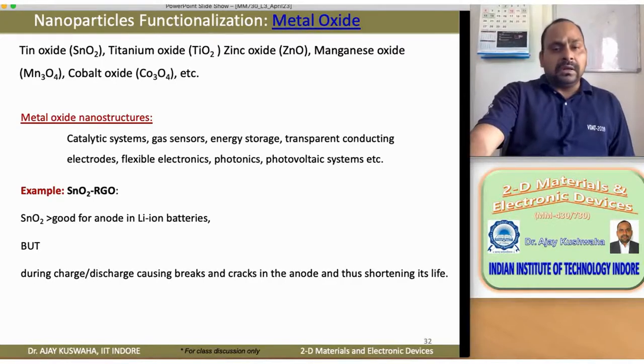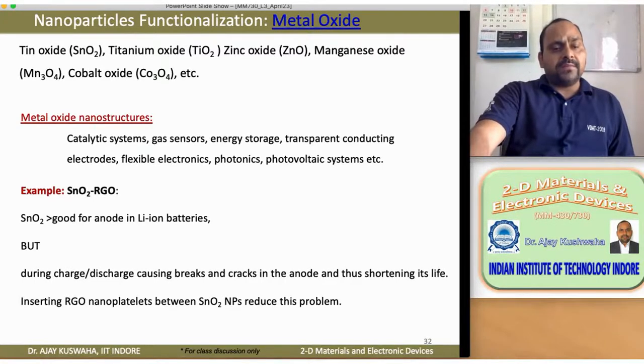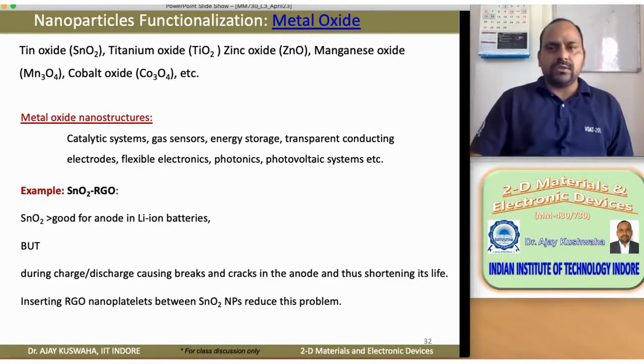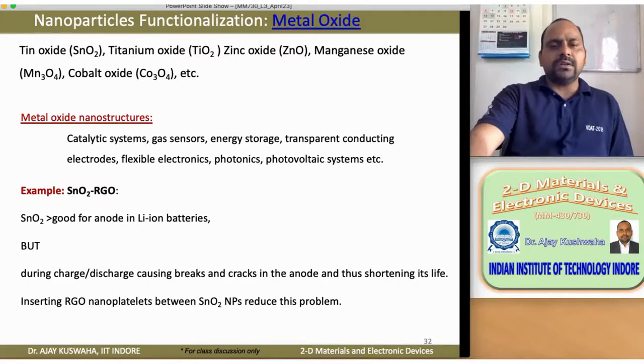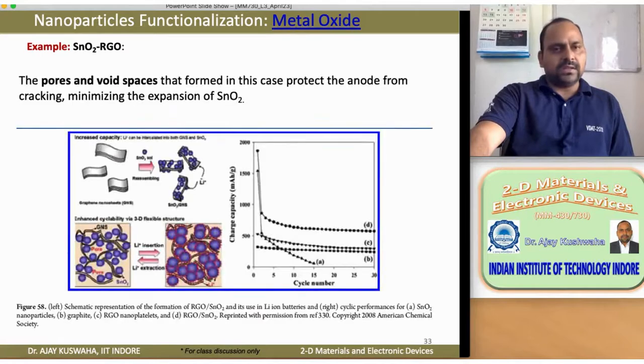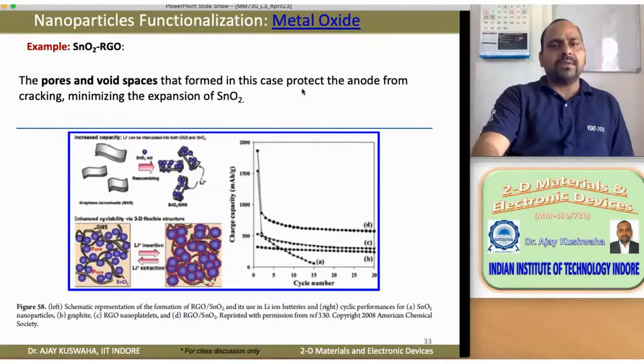So once they add the reduced graphene oxide between the tin oxide nanoparticles, basically your system is overall tin oxide nanoparticles, and just in between they are adding some amount of reduced graphene oxide, and they observe that this problem is solved to a large extent. Here this is the example, the pore and void space that form in case protect the anode from cracking, minimizing the expansion of SnO2.